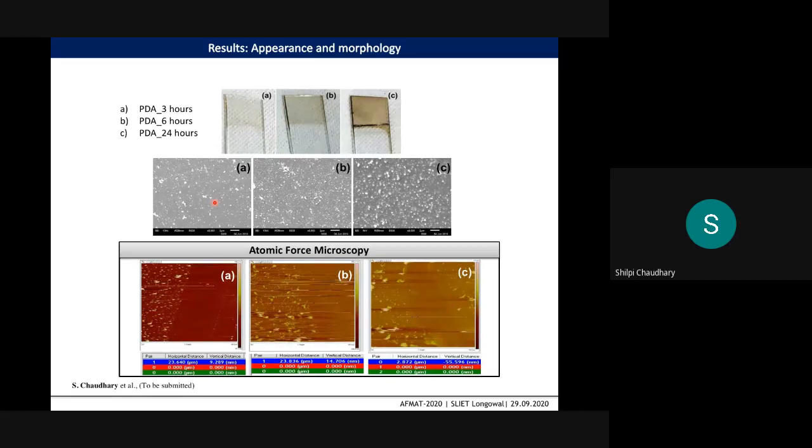Anyway, we have also done some atomic force microscopy measurements to see the thickness of the deposited films. What we have done is AFM measurements in contact mode. First, we made a fine scratch on the sample with, let's say, a tweezer. This is hands-on practice, how sharp an edge you can make. And the measurement was done perpendicular to the scratched line.